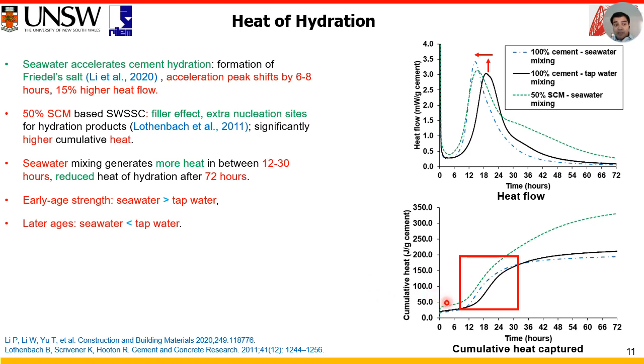However, it was interesting to see that the seawater generated mixes produced more heat in between 12 to 30 hours. However, after 72 hours, the seawater mixed concrete produced less heat compared to the controlled tap water based mix, which indicates the early age strength improvement of seawater and the later age strength decrease by using seawater.